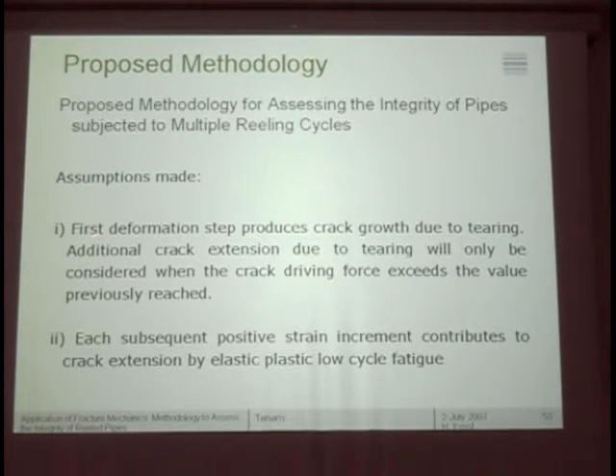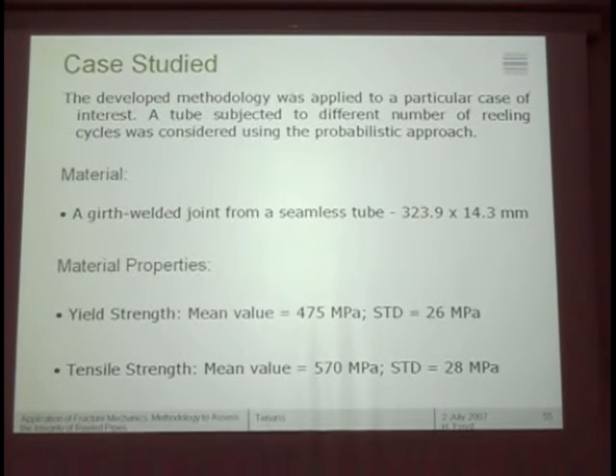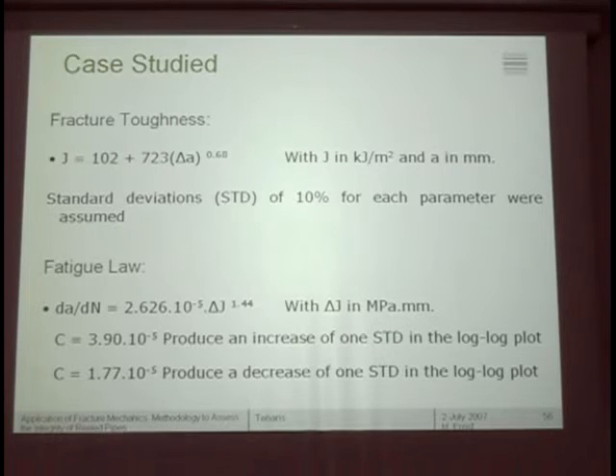So with this, the assumptions made as well, I don't want to repeat everything about the material R curve, because it is the whole methodology. We run a particular case, a material, again the same material as before, the material properties are the same as before. The fracture toughness given by this equation that we measure experimentally, and we put there a standard deviation of 10%, because usually you don't have so many resistance curves to have a real statistical measurement of them, so we have to invent here a number of 10%, whereas for the other parameters we did have some realistic numbers. And the same thing for the fatigue law.